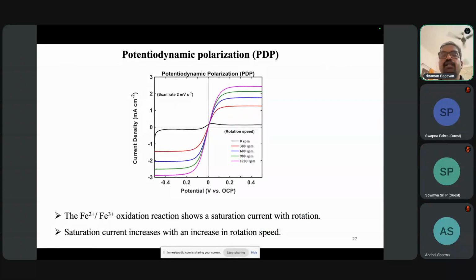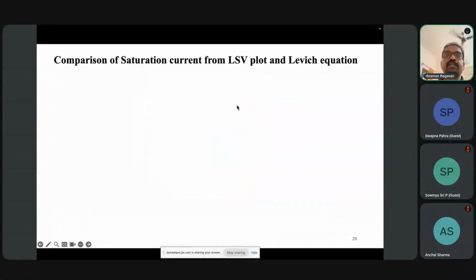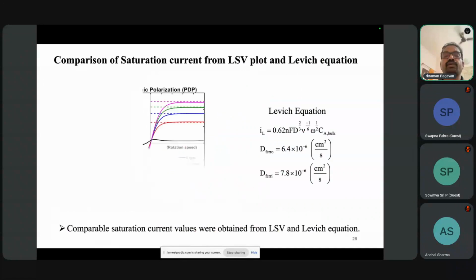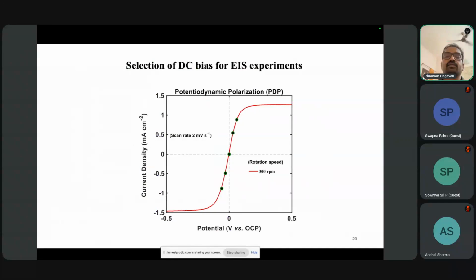And then when I increase the rotation speed to 600, 900, 1200, you see that the limiting current goes up. But there is not much change in this region, because this is a kinetic region wherein only the potential influences the current, not the mass transport. So the mass transport influence you will see very much in the limiting region. This is the experiment that we have done. Now what we do, we can do an impedance study at 4 or 5 different potentials along this LSV, linear sweep voltammetry.